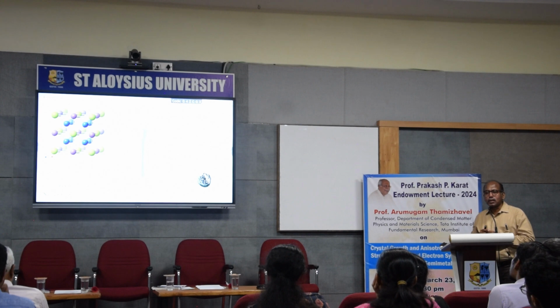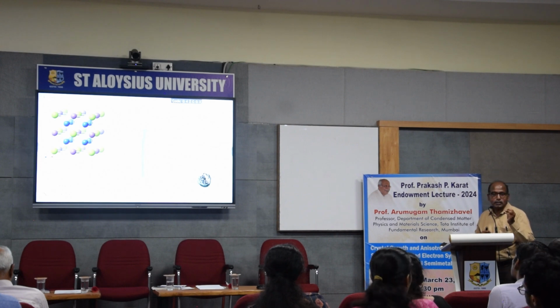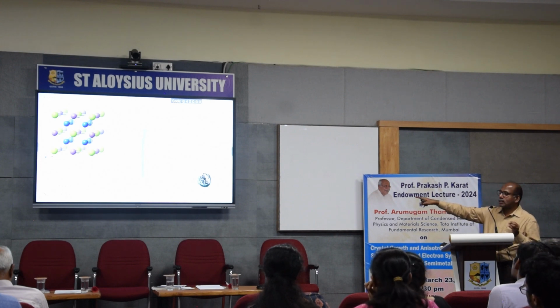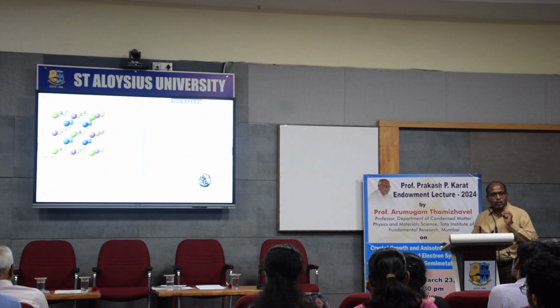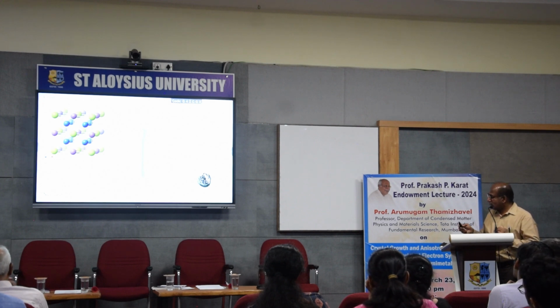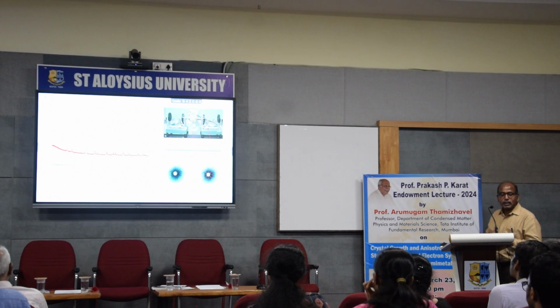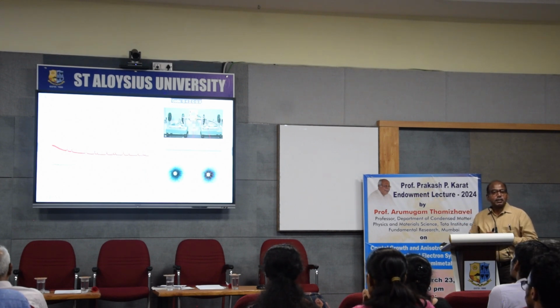So if I show this one, you have seen beautiful crystals of aluminum oxide, which look like jewelry. But this does not look like a crystal. So you will not accept that it is a crystal. But I have already explained to you that anything which produces diffraction spots is single crystalline. So the first thing I did was a X-ray Laue diffraction, and the bottom one shows the diffraction pattern. It shows a beautiful diffraction pattern, which confirms that this is a single crystal.